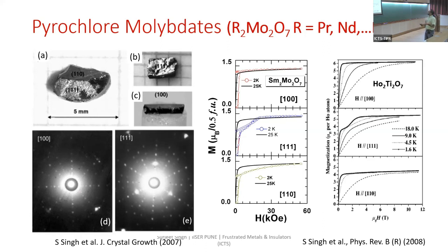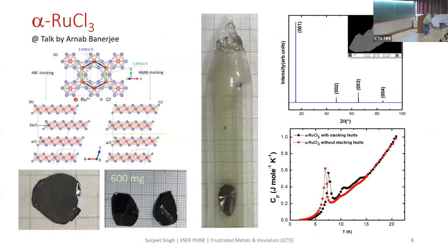So it shows an easy axis along the 100 direction, which is seen over here, and a step-like transition, which corresponds to a transition from 2 in 2 out to 3 in 1 out state. And then along the 110, you get the hard axis. So this was a bit technical, so let's move out.